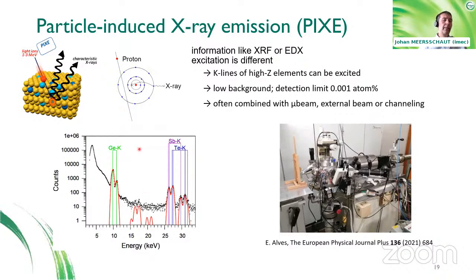On the one hand, the advantage of PIXE is that the particles emit very low Bremsstrahlung radiation. The Bremsstrahlung is induced by the change of the velocity, and the change of the velocity of this particle when it is transmitted through the sample is much lower than, for example, for electrons, which are much lighter particles as compared to these heavy protons.